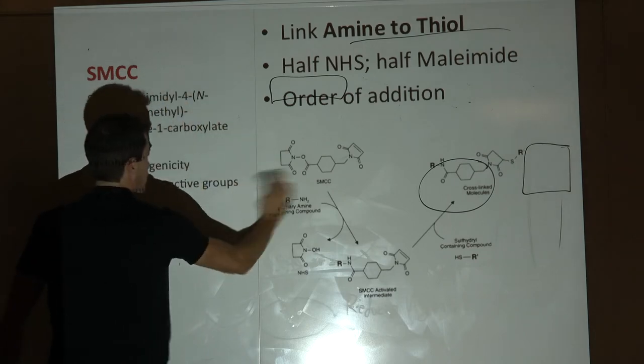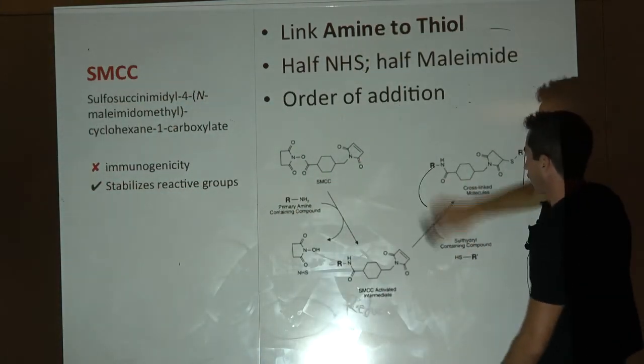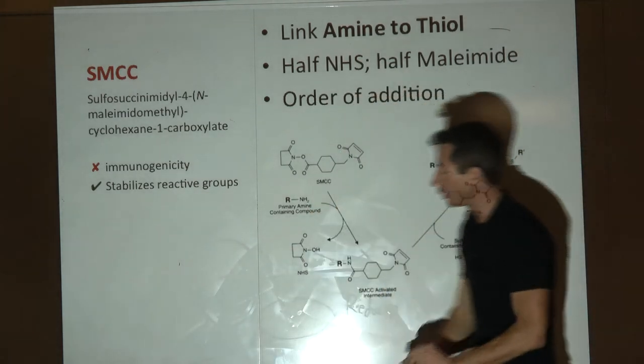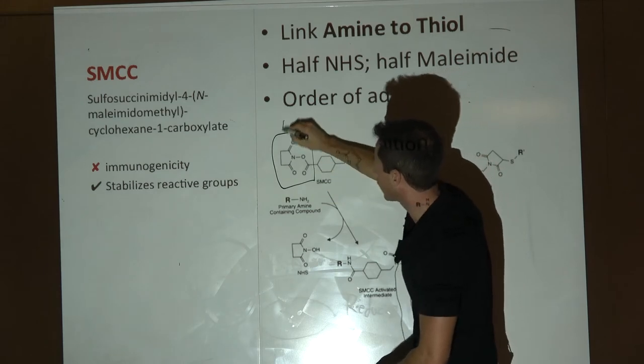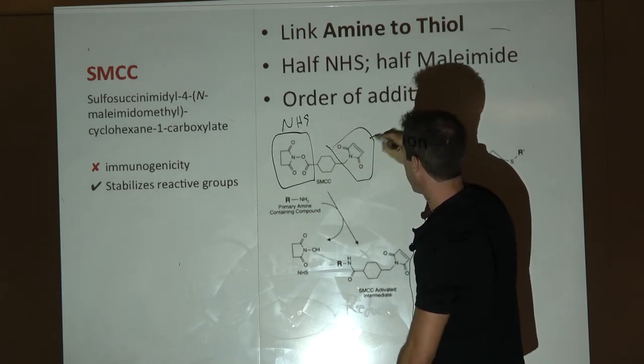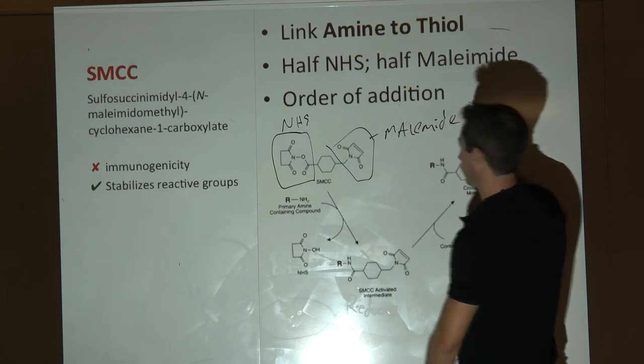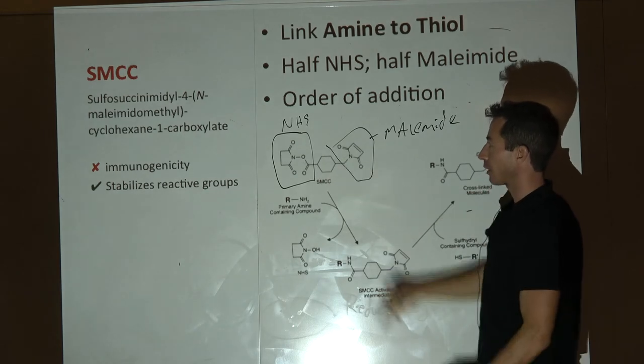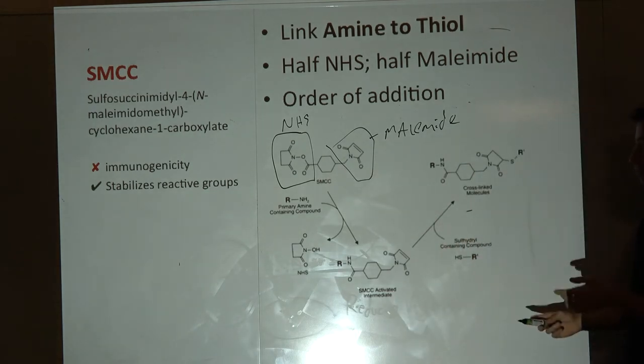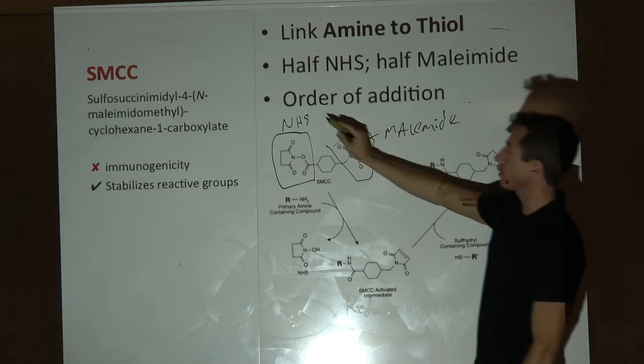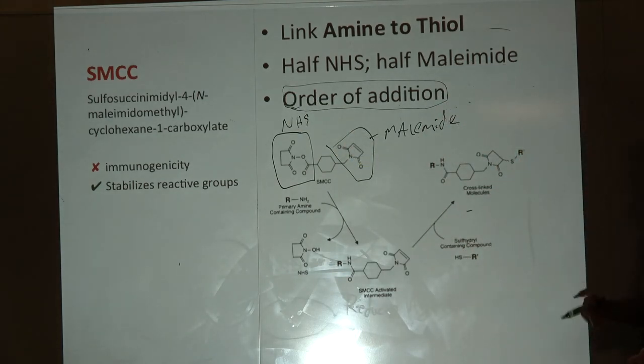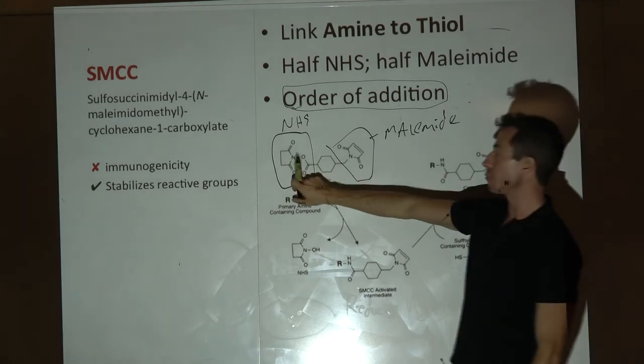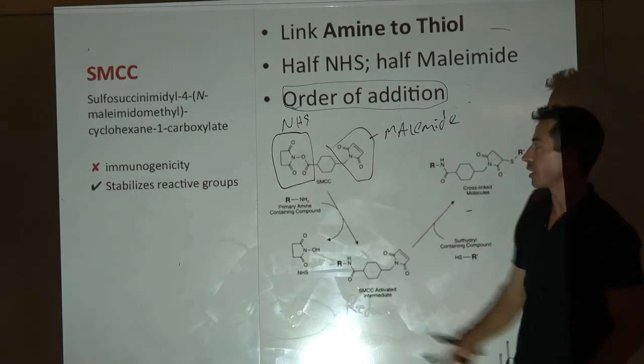SMCC is another really good one. This binds amines to thiols. If you look at this, this side is NHS and this side is your maleimide, linked through cyclohexane. That's pretty cool because now you can take something with a thiol, something with an amine, and put them together. The order of addition can be important here.